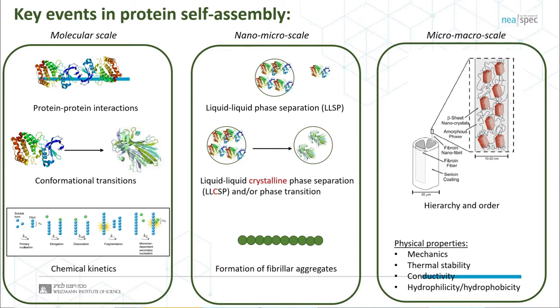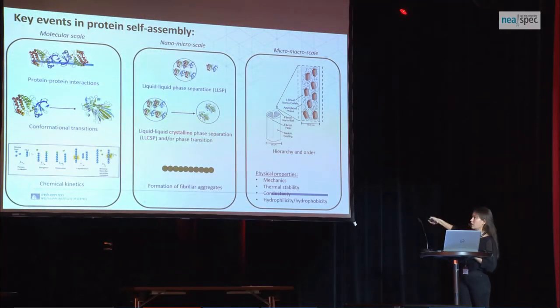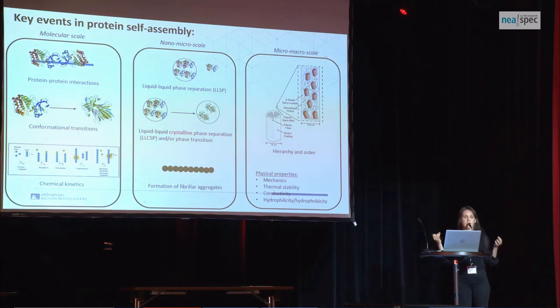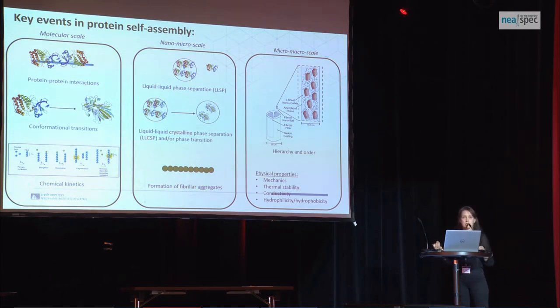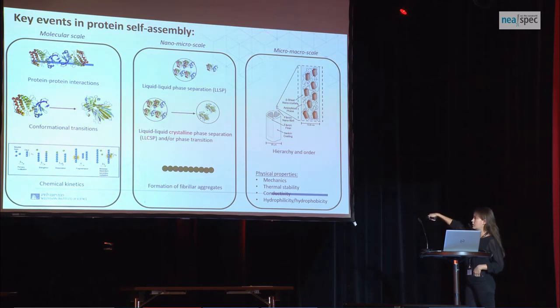Liquid-liquid phase separation occurs when we have a highly concentrated protein solution and, under certain conditions that vary between protein species, there is spontaneous formation of a condensed phase where proteins are sequestered into membrane-less vesicle-like compartments. The concentration is so high it drives interaction and conformational transition from the native fold to a beta-sheet-rich structure. There is debate about whether this involves liquid-liquid crystalline phase transition and whether it involves protein crystallization.